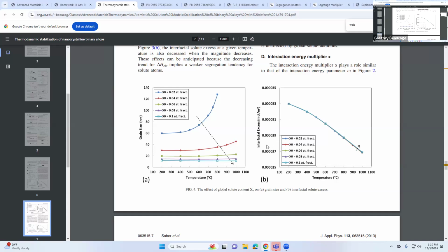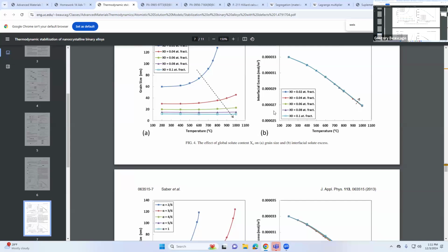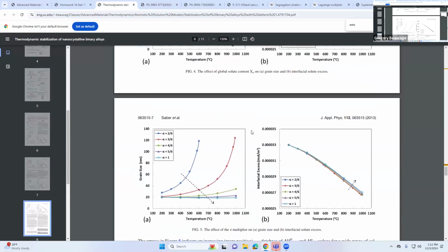And then in terms of the interfacial excess, it doesn't make any difference, the mole fraction that you put in. He says this matches with the Langmuir-McLean model, which means you're already working at a concentration where you saturate the surface with a monolayer. It doesn't matter how much more you put in. You're in the pegged out part. When you're over here, your surface isn't covered, and then the surface covers, and then it's flat. So he's saying putting more in beyond 0.02, it's already completely covered. It doesn't change it. Right, so that's his Langmuir-McLean model.